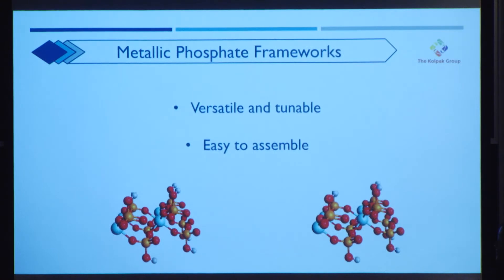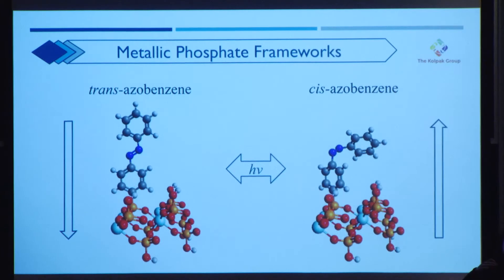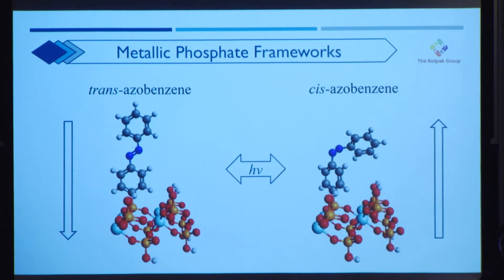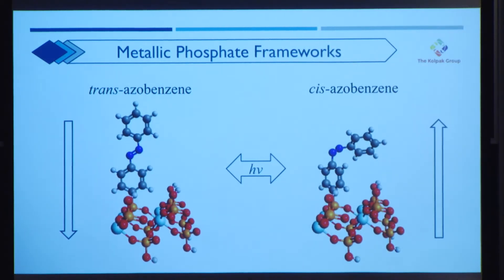We took these metallic phosphate frameworks — such as the zirconium phosphate framework shown on the screen — and attached azobenzene in both conformations. These frameworks are able to increase delta H in both directions: for trans-azobenzene, the rigid framework stabilizes it, increasing delta H downwards; for cis-azobenzene, dense packing creates repulsions as the molecules fold over and clash, raising delta H upwards. We had six major structural variations, and for each we created two versions — trans and cis — then used density functional theory to find the ground level energy states and thus identify delta H. We iterated these unit cells in all three axes to create stacked sheets of these structures.